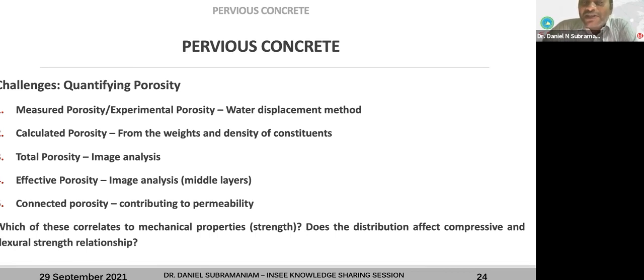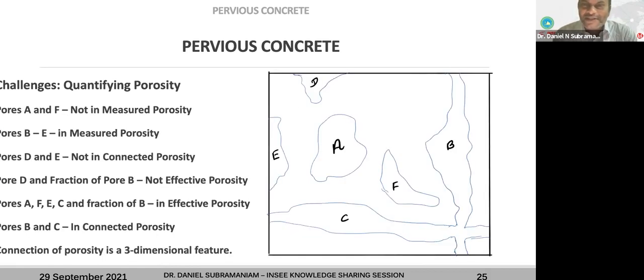Okay, so which of these actually correlates to mechanical properties? Does the distribution affect compressive strength or flexural strength relationship? Right. So if you look at this picture, the pores A and F are actually in the middle of the cube. They are not exposed to any sides. So now if you dip this concrete cube into the water, it is not going to enter A or F, right? The water will enter through B, C, E, and D, but it's not going to enter A and F. So when you do the computation of porosity, A and F will be considered as solids. So the measured porosity that you're going to get by experiment is going to be an underestimation of actual porosity.